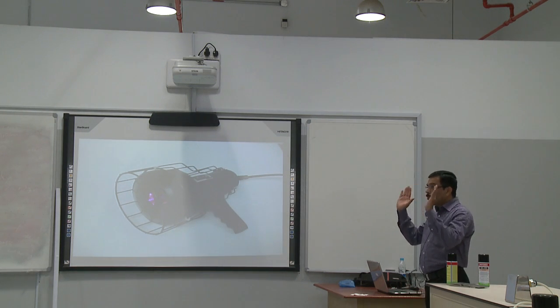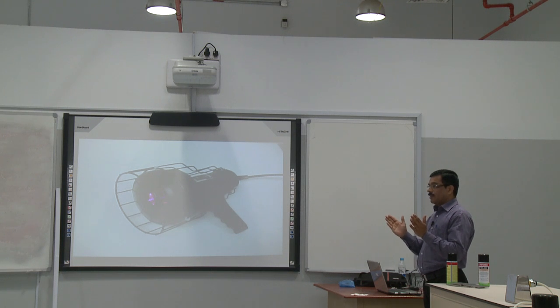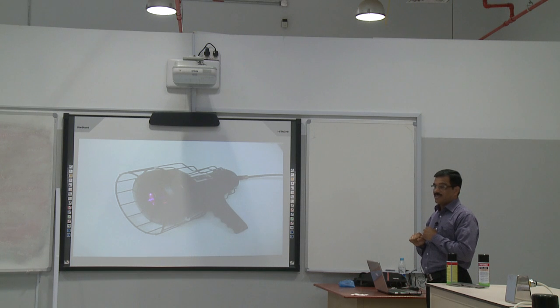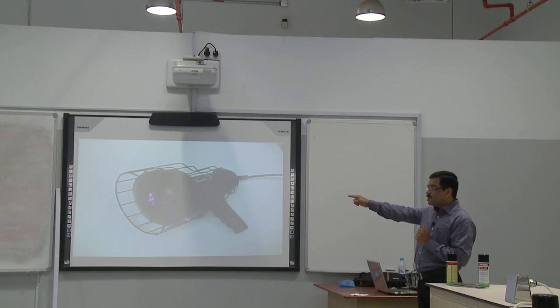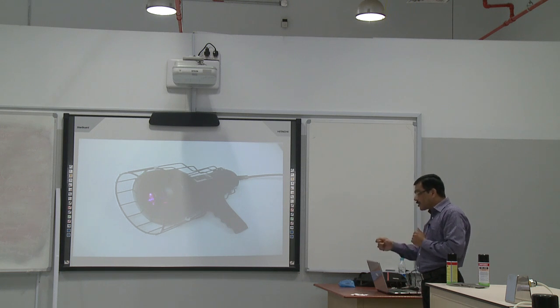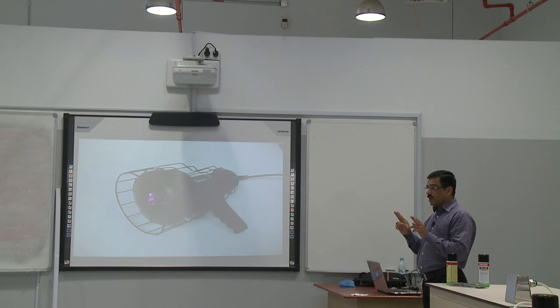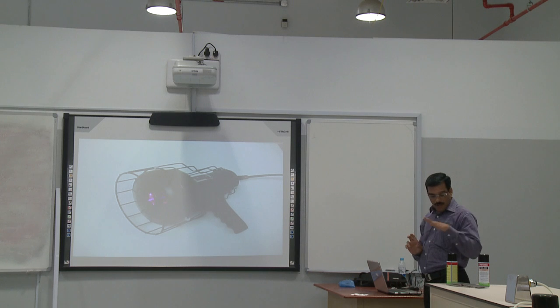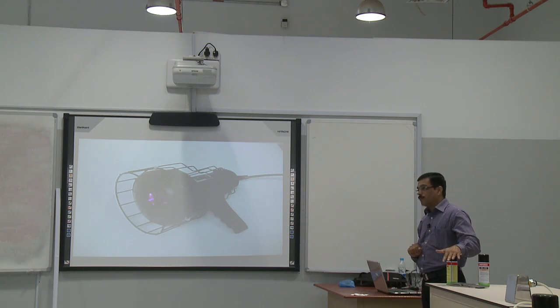And the area should be dark. The white light intensity should not exceed 2 foot candles. That means almost a dark area. We can use this fluorescent lamp, then you can see the indication with a yellow-green fluorescent color. So that is the type 1 PT chemicals.